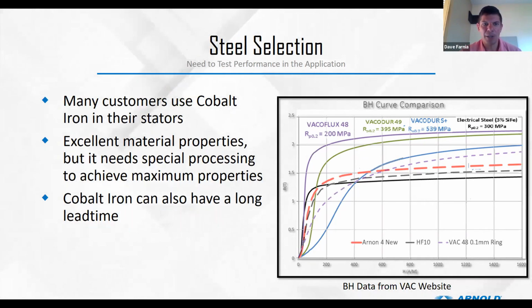The challenge, though, is that they really need some special processing to achieve those properties. So you have to do the heat treat. You have to be very careful with how much stress you're inducing in cobalt iron. So there is some special processing that goes along with it. At the same time, cobalt iron can have a very long lead time. So these are things that should be factored into the design. Where is the design? Is it rapid? Do you have to get a prototype up and running for a demonstrator? If so, it could take longer than expected to get some of these materials in.